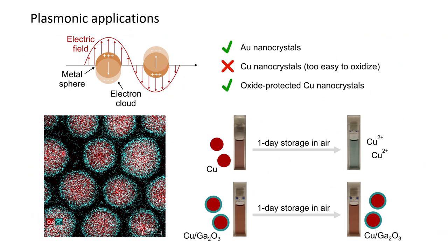So you see here a compositional map. Each of these nanoparticles has a small crust of gallium oxide. How did we make it? We just add a very little of the gallium salt, so we collect gallium only on the surface and oxidize it at ambient. And now you see this flask here: after 1 day of storage, the copper only would get oxidized, and this would give us the blue-looking solution, the complete oxidation of copper nanoparticles to copper 2+.